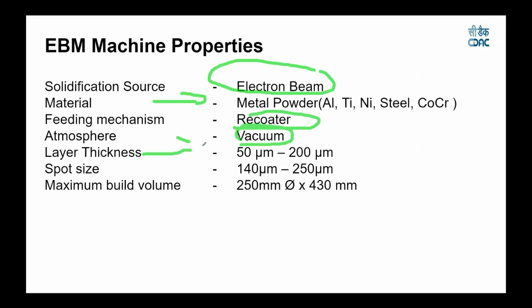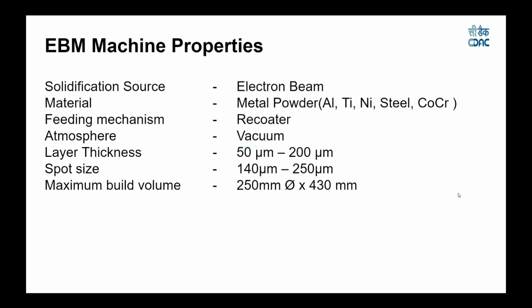Layer thickness, we have 50 microns to 200 microns. But in case of SLM, we have 20 microns to 100 microns. Here the layer thickness is more, so we cannot print much finer parts compared to the SLM process. Next, the beam spot size is from 140 microns to 250 microns, and the build area is 250 by 430 by 430. So these are the machine properties of the EBM manufacturing process.